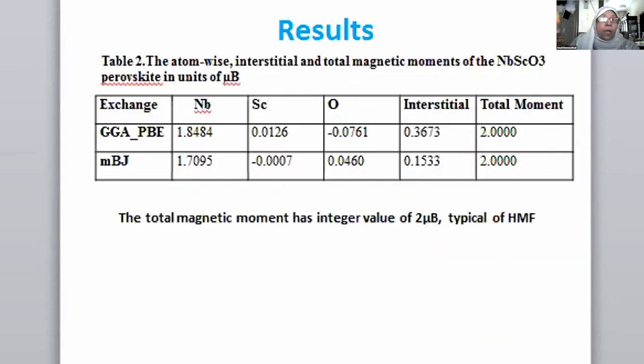Here we can see on the table actually the magnetic moments. Yes. So if anybody did not get the density of states clearly from the picture, we can see it here in actual values. So the niobium magnetic moment is 1.85. And we are having scandium is 0.01, which is very, very small. And the oxygen here is very small also, 0.07. This is with the GGA results. In the interstitial space, we are having also 0.36 magnetic moment, and the total moment, which we are very much interested in, should be a half metal value. For a half metal it should be an integer value, which is 2.